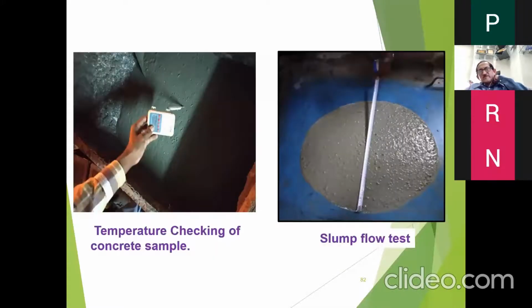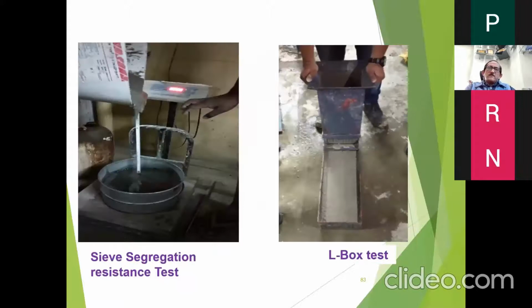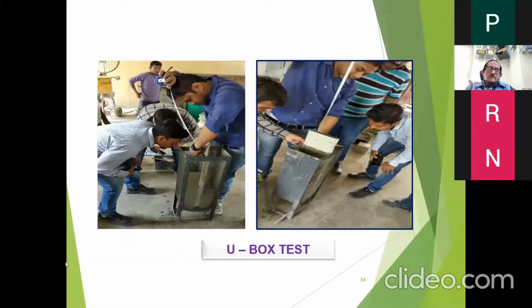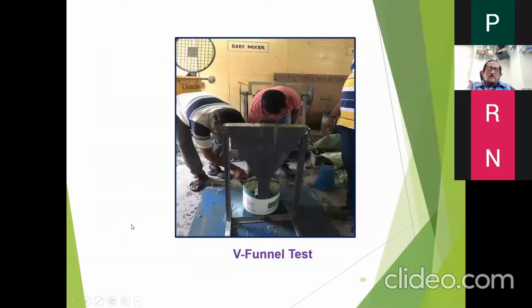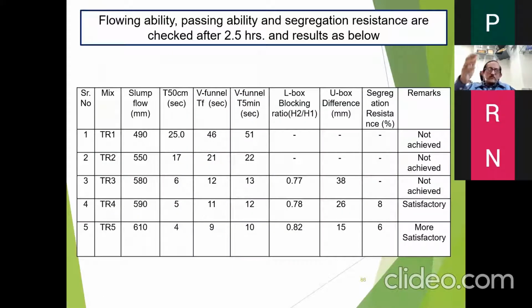So temperature taking, slump flow test, and this is by taking the sieve segregation, L box. These tests we did. V funnel test. There are some videos also. If they are there, I'll show you afterwards. The slump flow test, flowing ability, passing ability were checked after 2.5 hours also.